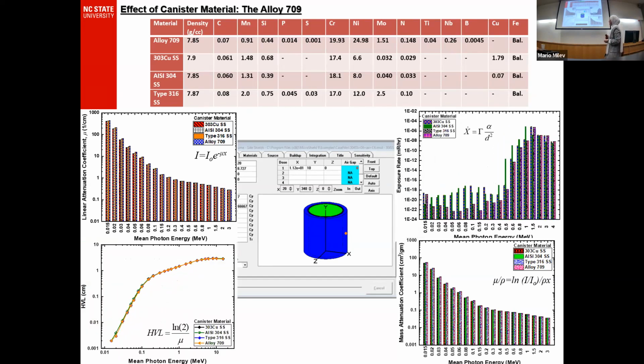Another property we look at is exposure rate, with buildup, compared to the other materials. We can see that the difference between the different stainless steels is significant at lower energies, but with increasing energy the difference becomes less significant. Also, alloy 709 still offered a better reduction in exposure rate compared to other stainless steel.